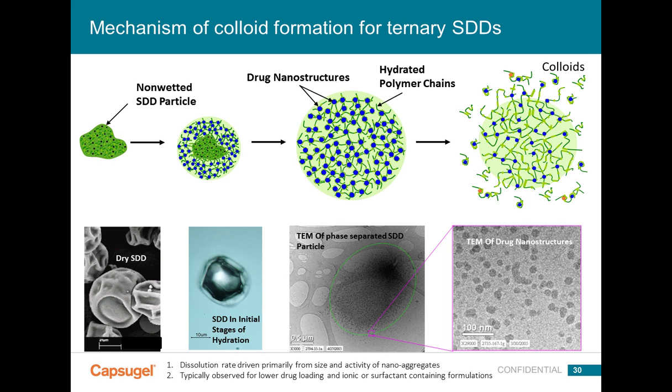There are two TEM images here, one of which on the bottom right is a little easier to see because it's zoomed in. But this is what we're able to see when these phase-separated drug-rich nanostructures form within an SDD. When the polymer fully dissolves, the drug colloids are then released into the media, as is schematically depicted in this upper right part of the cartoon.